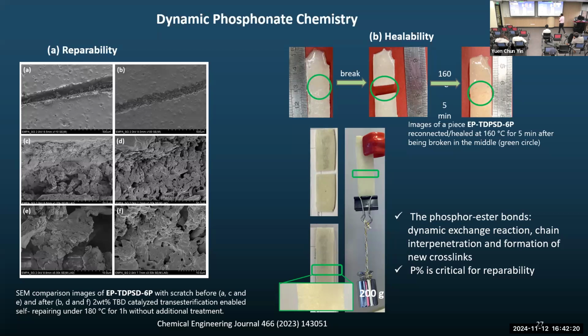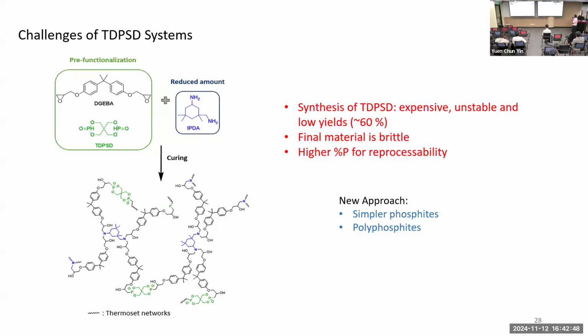Of course, the material is scratch resistant. You can see we made a big scratch and then tried to heal it. Obviously, it is not able to completely heal the structure because you removed material while you made the deep scratch. But you still see that it is able to recover quite a lot. And with repeated heat, you can break and recover the structure back and forth again and again, I would say, this epoxy.